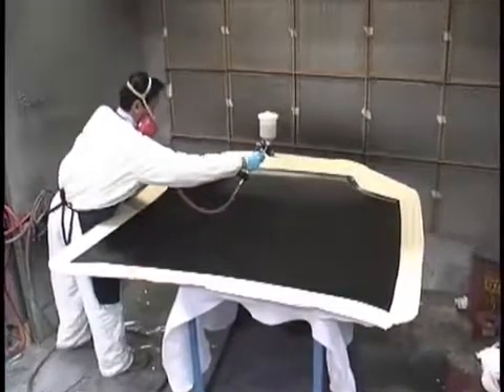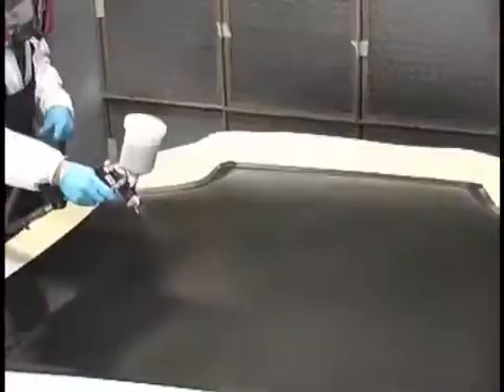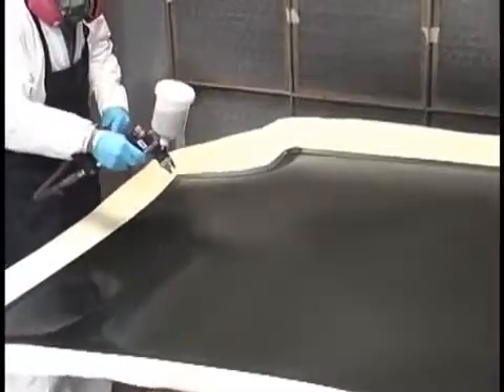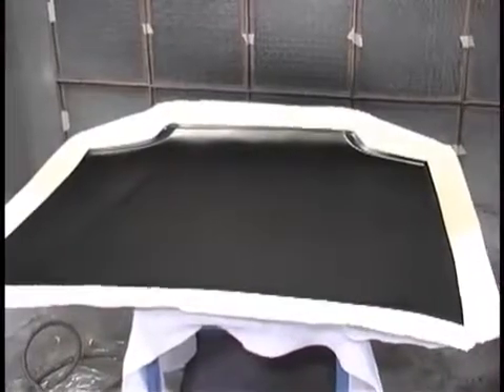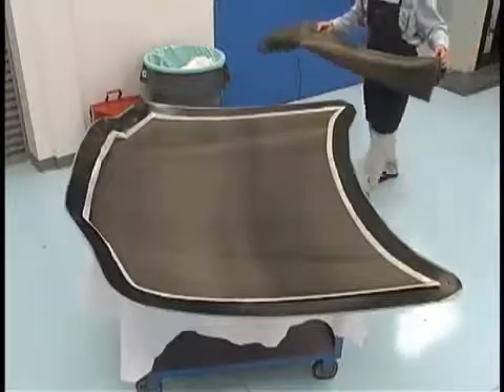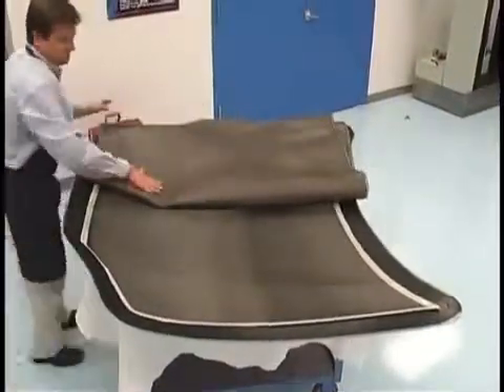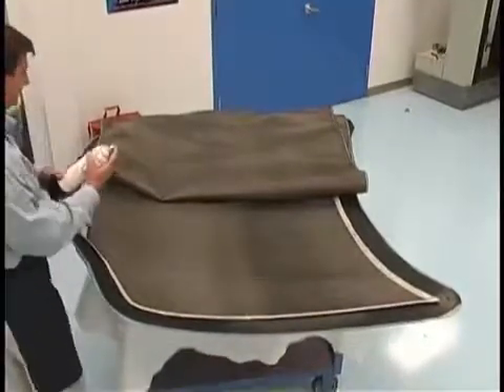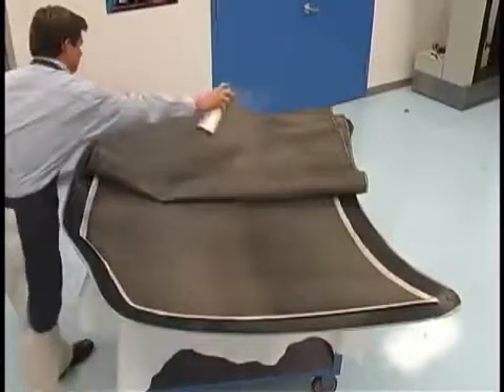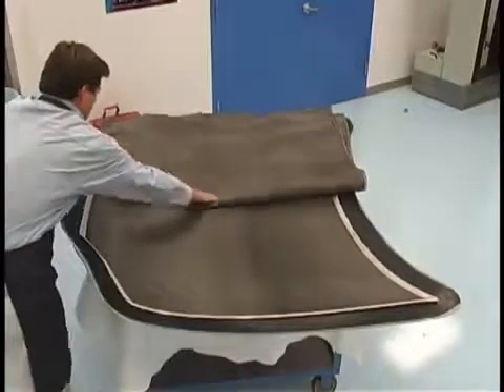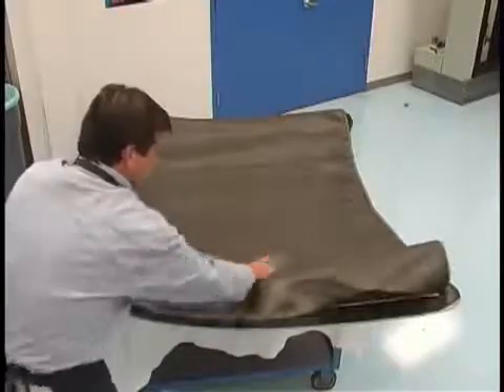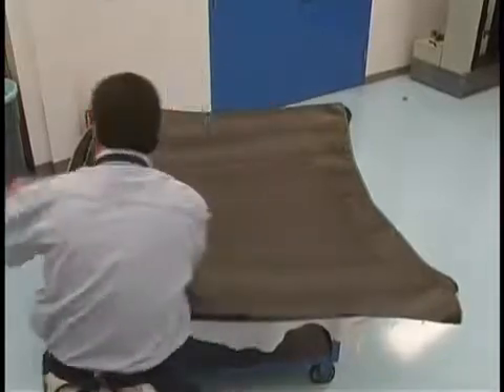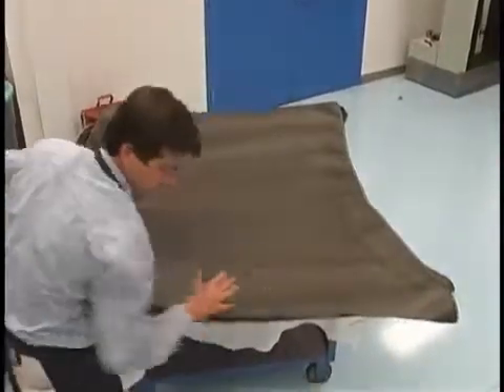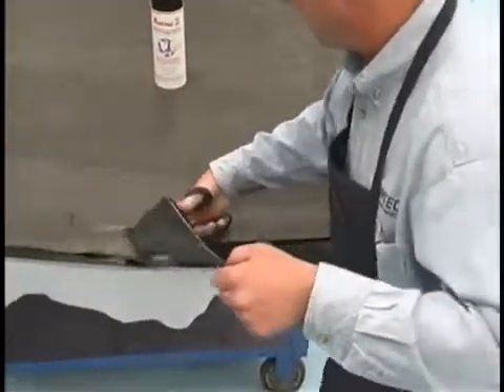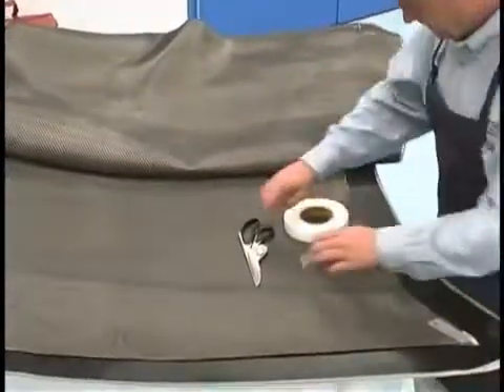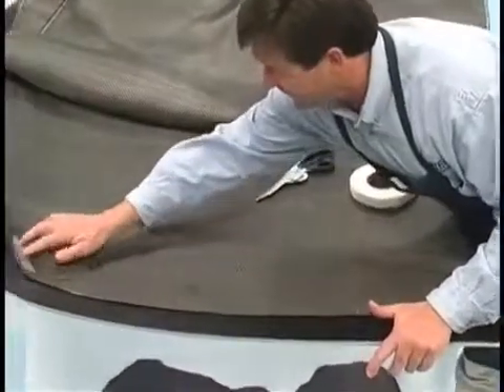Next comes the gel coat application, which is applied approximately 1 mm thick. Several layers of cloth are placed against the mold. Subsequent plies are held down using a spray adhesive, such as AirTac 2. The extra cloth is trimmed, leaving a clean part. Another way to tack down cloth is by using an adhesive mesh, such as Airtech's Tack Strip.